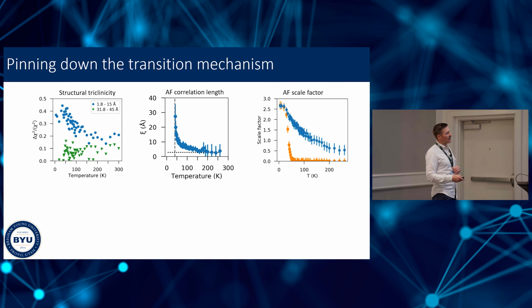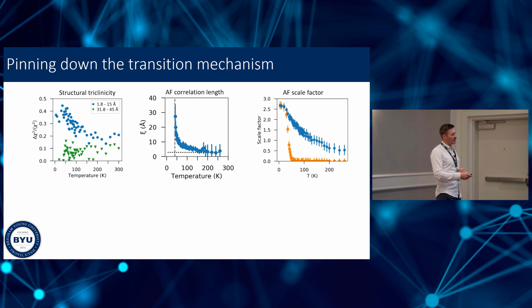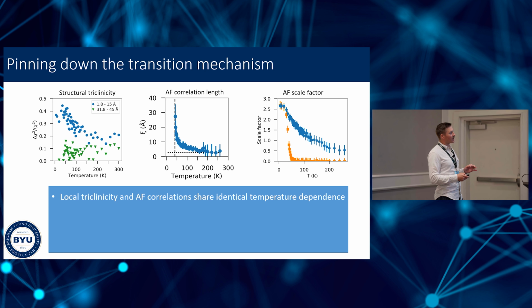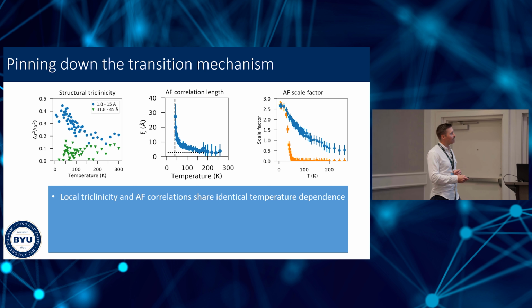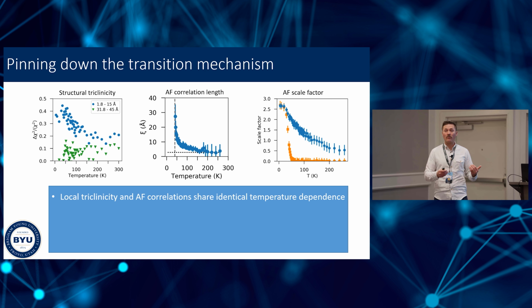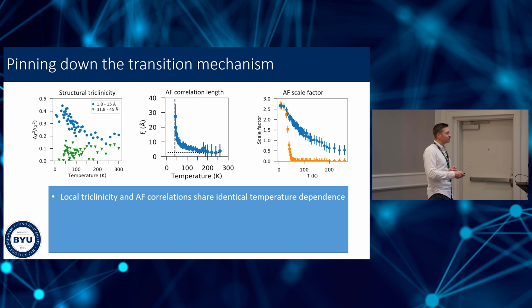So let's compare the temperature dependence of the structural distortion, that local triclinic distortion, and these local magnetic correlations. We see they share a very similar temperature dependence, right? It's right around 150 Kelvin that the correlations, which had plateaued at the nearest neighbor distance, now begin to grow beyond just the nearest neighbors. That's the same temperature where this local triclinic distortion begins to grow in magnitude.